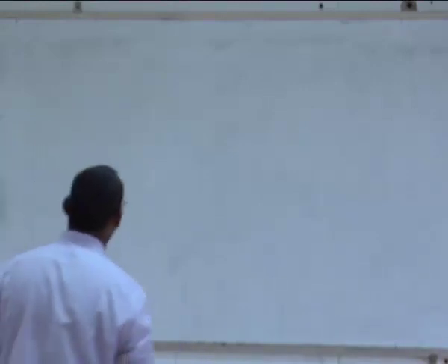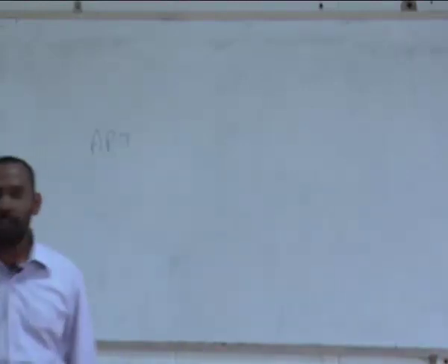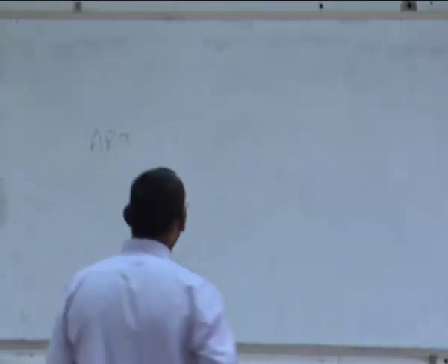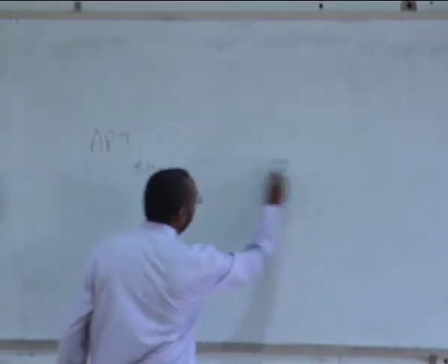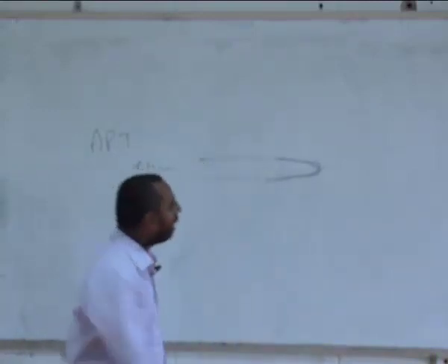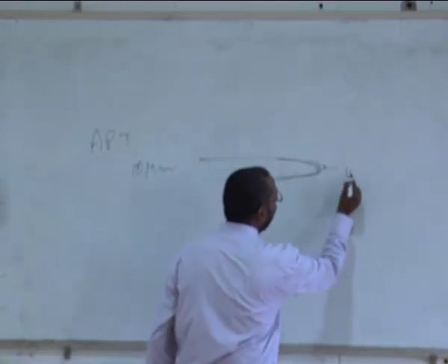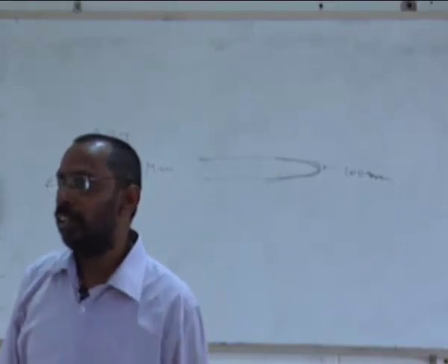Then I went to Japan for 2 years, working on a new technique called atom probe tomography, where we make a sample in the form of a tapered needle with a diameter of about 10 microns, and the tip will have a diameter of the order of 100 nanometers. This is a very tough job.